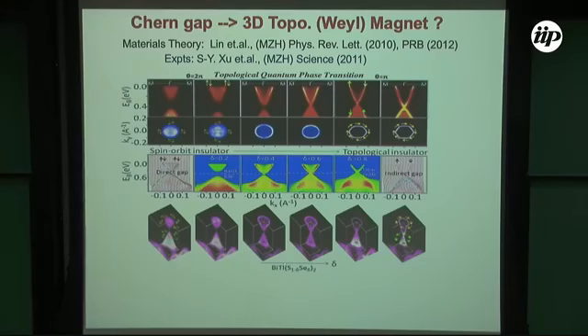So this is on a bismuth-based topological insulator where we are tuning sulfur and selenium. Selenium is heavy, it has large spin orbit. Sulfur has weaker spin orbit. So when there is stronger spin orbit, we see a topological state by spectroscopic measurement. And when we go to the sulfur end of it, we see that there's a gap. Otherwise, if it is topological, there would be a Dirac cone here. So in between, there is a transition happening, a band inversion transition. If you like, you can call it a topological phase transition.